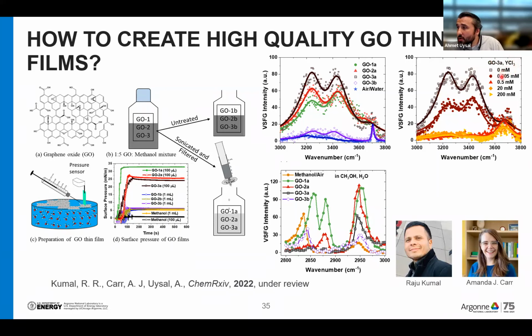We are increasing the bulk concentration. You remember these bimodal peaks from my previous data. That's what you see at the air-water interface if you have some charged film on the water. And then that signal goes down as you adsorb ions, again shielding the surface charge and also disrupting the interfacial water structure. But very interestingly, there is a very high frequency peak here in the graphene oxide system, which doesn't change. It is not affected pretty much by the ion adsorption.